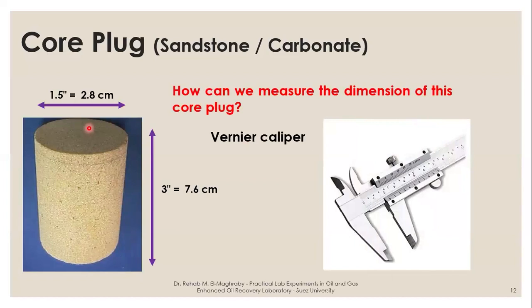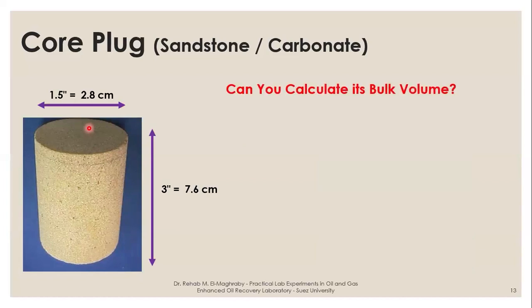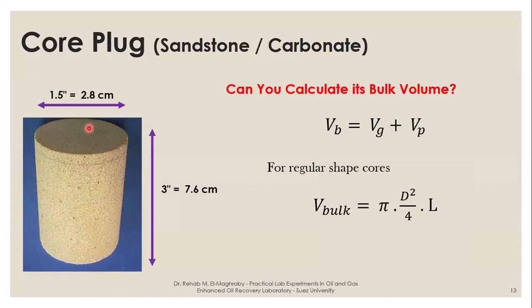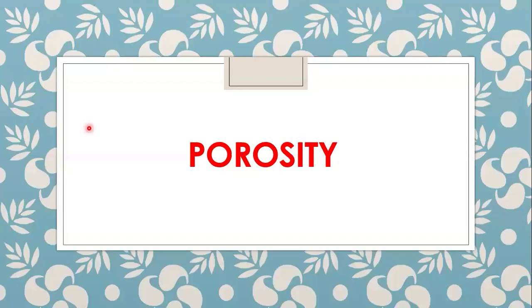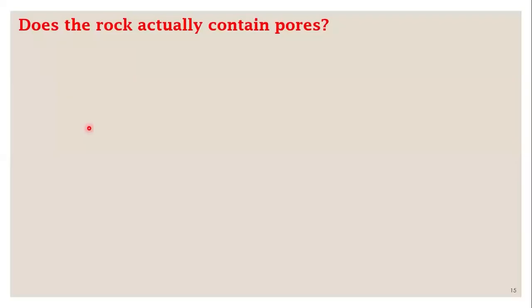We measure that using a vernier caliper. We can then calculate the bulk volume for this core plug, depending on whether it is regular or irregular. So it is a regular shape: π d squared over 4 times L. This is for the regular core plug. So now for the porosity measurement,